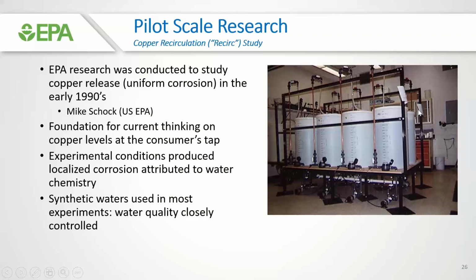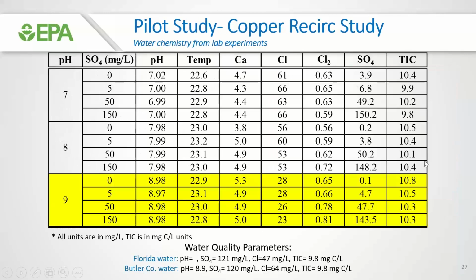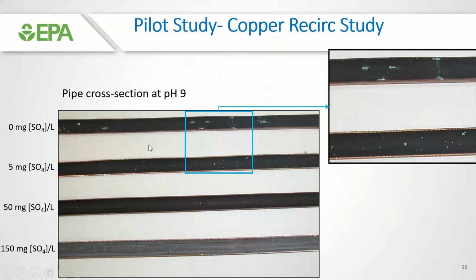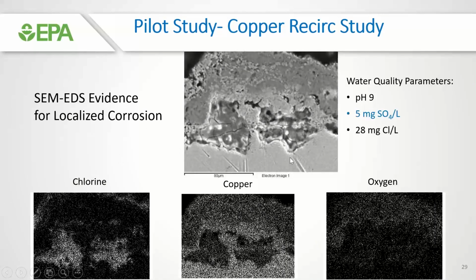And it worked amazingly well. I mean, it took several months for something to develop, but it's something that might work if you're in a desperate situation. We did these experiments, again, different TICs or DICs, different pHs, 6, 7, 8, and 9, different sulfate concentrations. But all I wanted to show you here with these experiments was that at pH 9 and low DIC, what we found again are these little splotches of corrosion byproducts. And again, when we do our cross sections and look at what's going on, we see below those caps, in the low DIC waters at high pH, sure enough, we see the local attack.